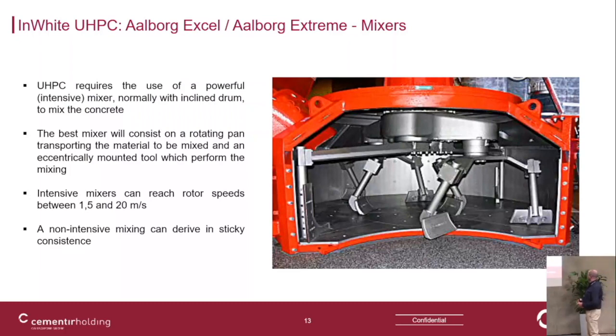To mix this kind of products, you need a mixer that is really powerful, because the reaction of the superplasticizers can take some time, and so the most suitable mixers are the pan mixers. And you have also to consider that the capacity of the mixer is, in traditional concrete, maybe 500 liters. Then you have to consider that it's almost half of the quantity that can be mixed in this kind of mixers.